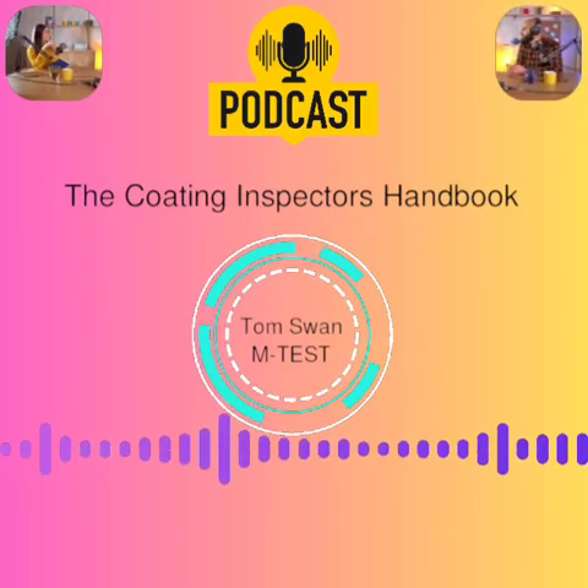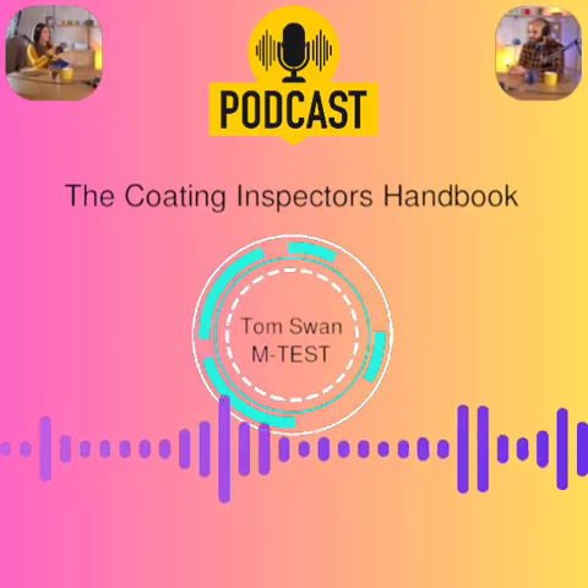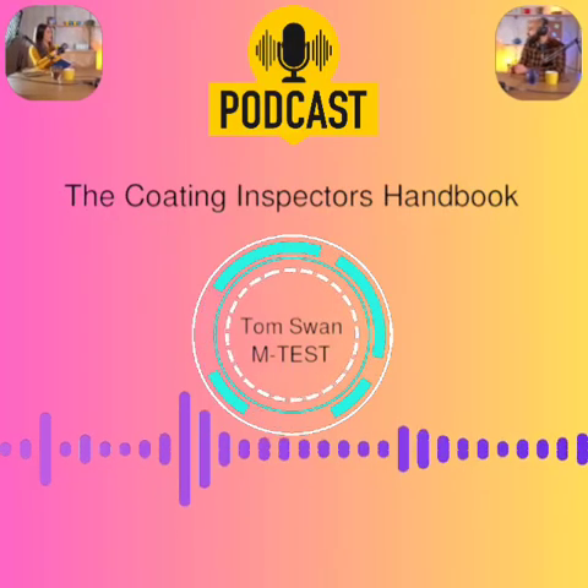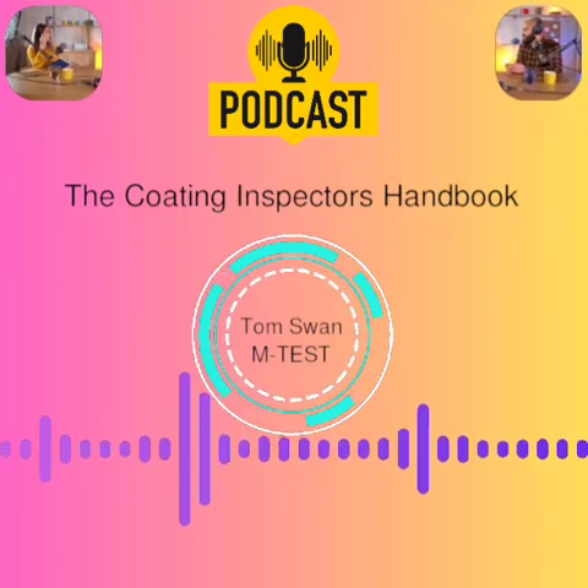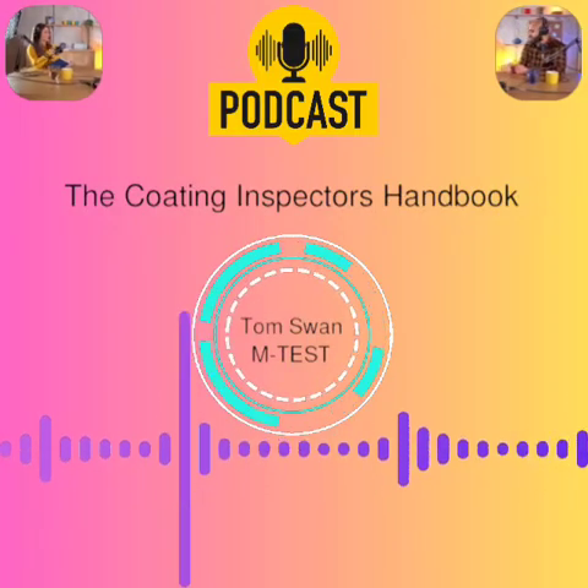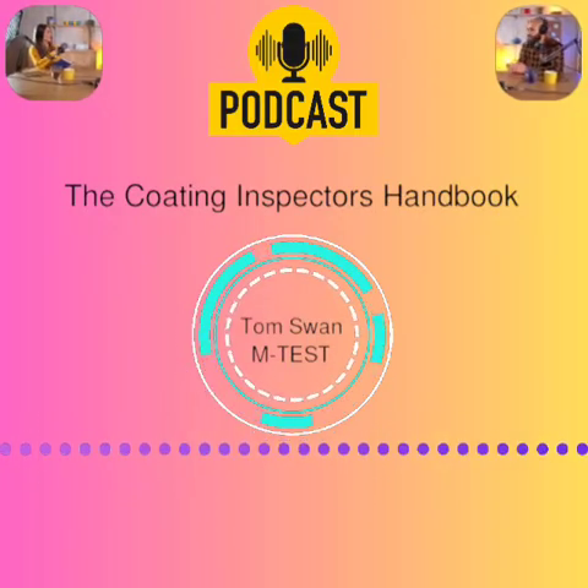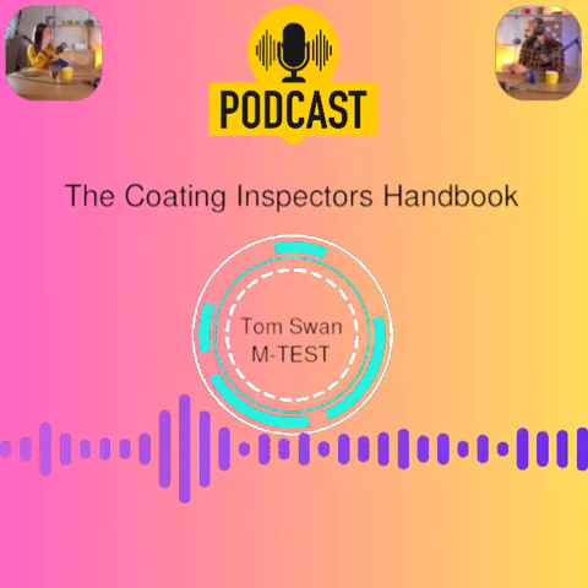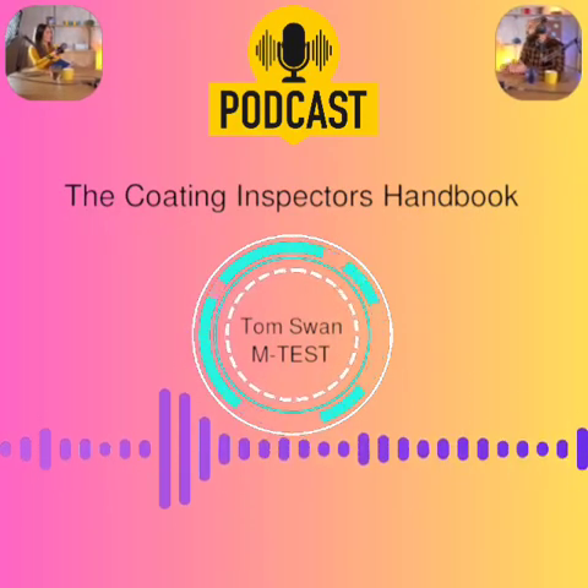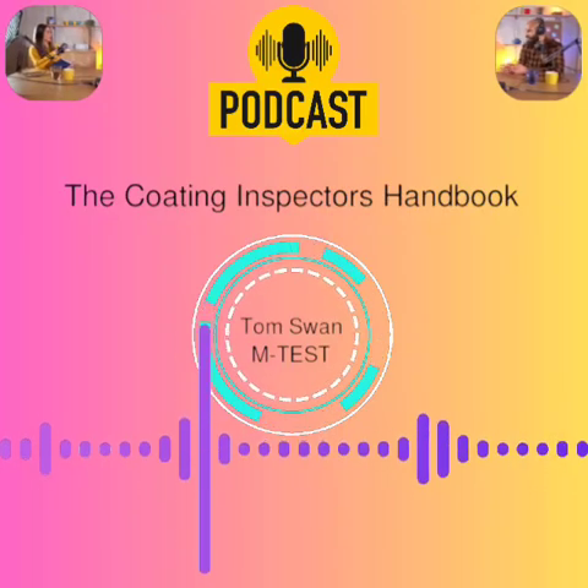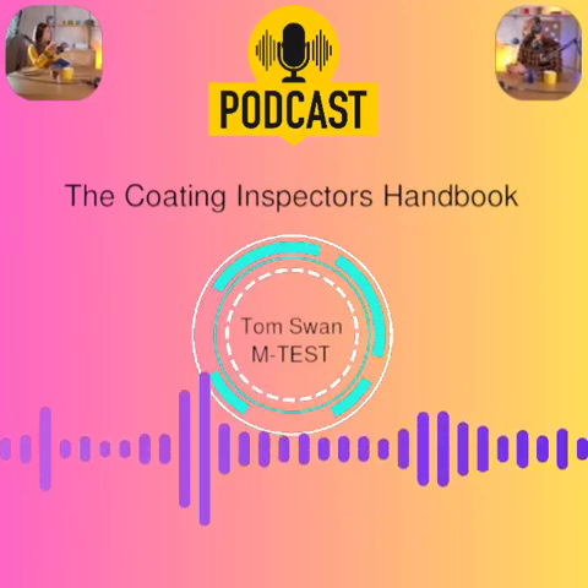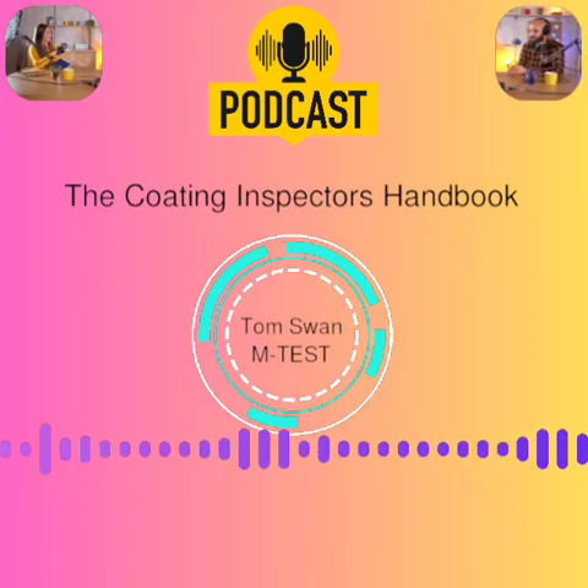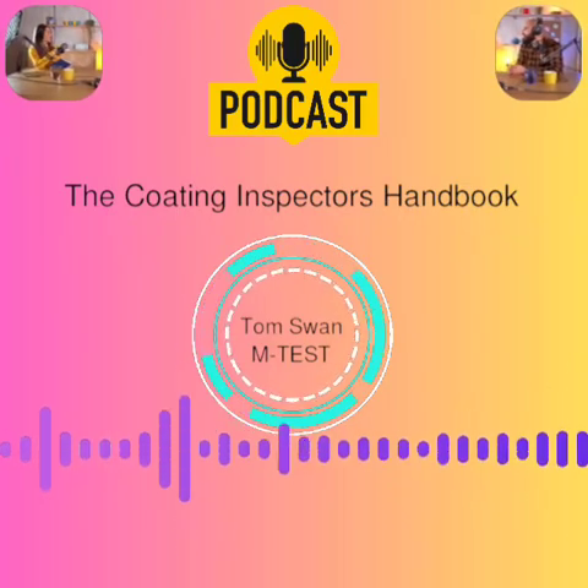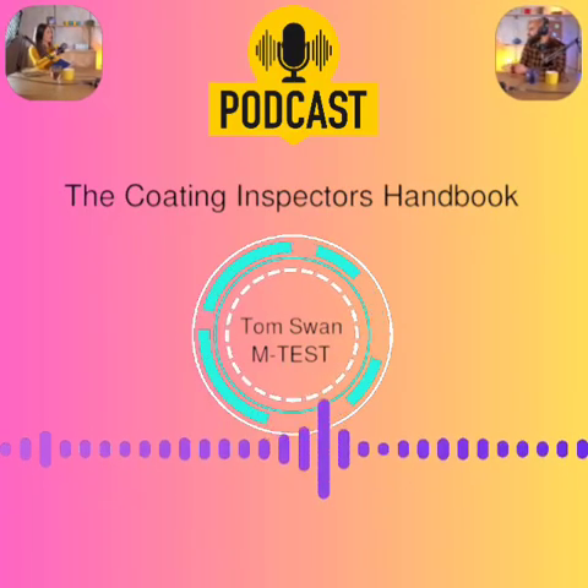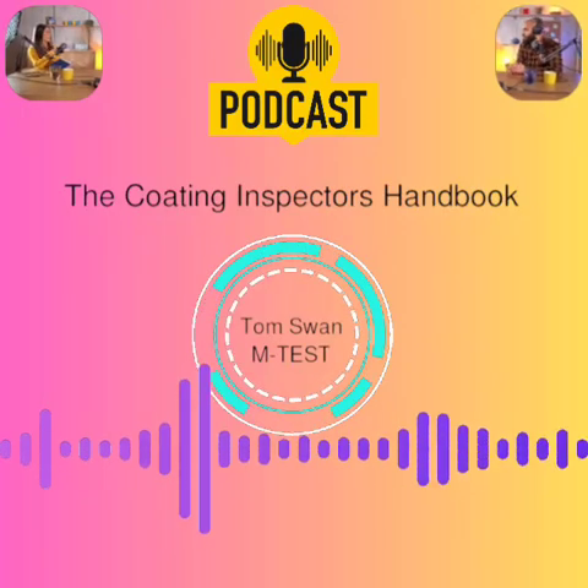When do you really need white metal, SP5, versus near white, SP10? Generally, SP5 for the most critical stuff. Immersion service, metallizing, some inorganic zincs. SP10 is often fine for atmospheric exposure, but ultimately, the coating manufacturer makes the final call for their product in that service. And on new steel, it might be hard to tell the difference visually between SP5 and SP10 if there was no rust or scale to begin with. What about achieving SP11? Power tool cleaning to bare metal with a profile. That's tough. Requires specific tools. The handbook mentions the Monti MBX bristle blaster as one tool often recommended for achieving that required 1 to 3.5 mil profile along with the visual cleanliness.